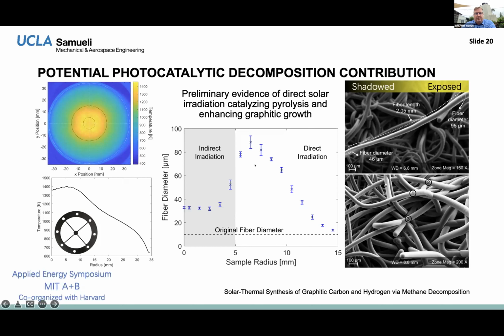But we actually built a shadow mask. It's shown down here, and you see that it has this central circle that's just 5 millimeters in diameter or less. Then we extracted a sample that came out of that process, and we looked at the growth, so the size of the fibers, as a function of radius from the shadowed region. So this is the indirect, and then the directly irradiated parts. And we see a very pronounced effect.